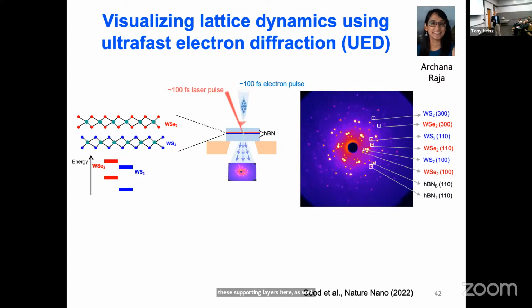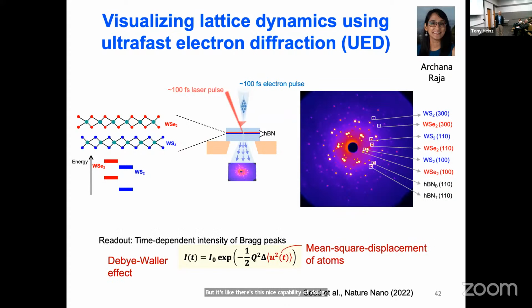But at SLAC, there's this nice capability of doing electron diffraction with a short pulse. So the result of that is that you actually can trace the amplitude of these spots as a function of time. And when the atoms are excited by phonons, they move, and the Debye-Waller factor reduction comes into play. So that actually gives us a way of looking at the evolution of the vibrations, and we can see where the energy is deposited that accompanies this current flow.